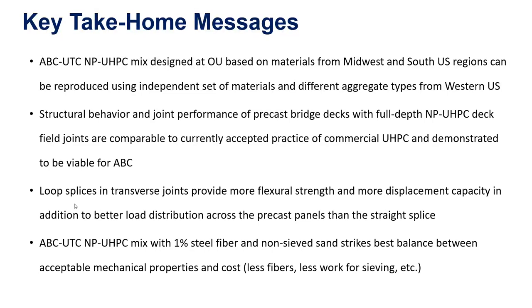Based on our comparison, loop splices are slightly better than straight splices. Additionally, the non-proprietary mix with 1% steel fiber and non-sieved coarse sand strikes the best balance between acceptable mechanical properties and cost, since it requires less work for sieving and material preparation, and fewer fibers — translating to a more economical mix. We recommend this configuration for this application.